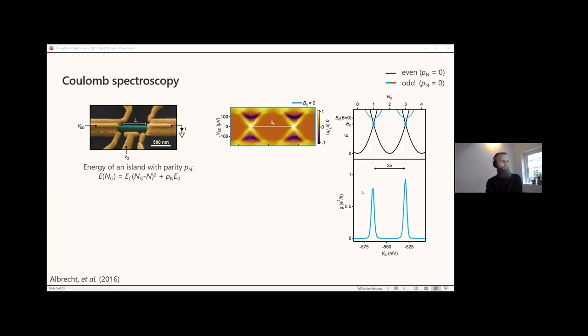Great. Now, if we apply a magnetic field to the system, the subgap state, as shown before, spin splits, and then decreases in energy, at least one of the branches. Once the odd parity parabola decreases below the charging energy, the island is able to be oddly occupied, which effectively splits these Coulomb peaks, and then we start seeing the odd Coulomb diamonds.